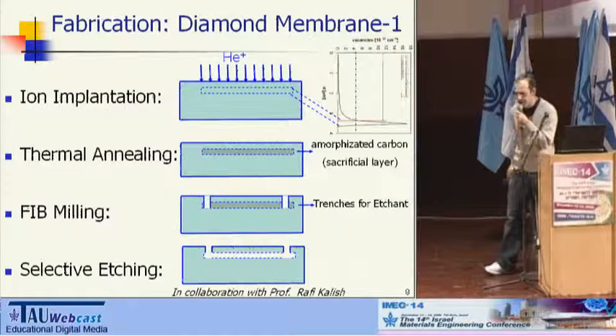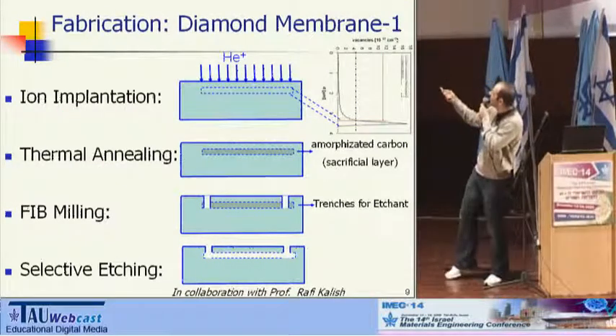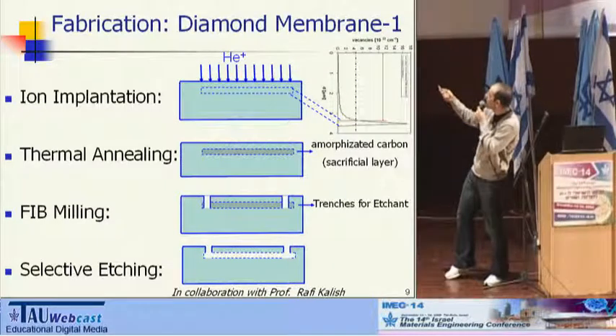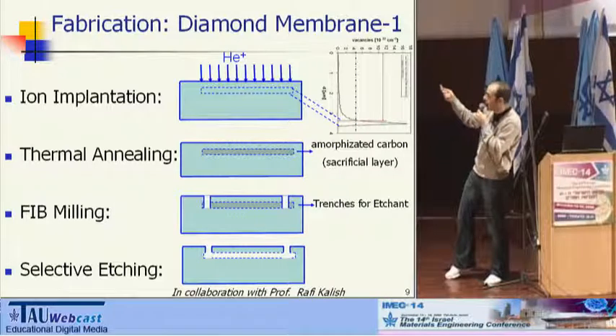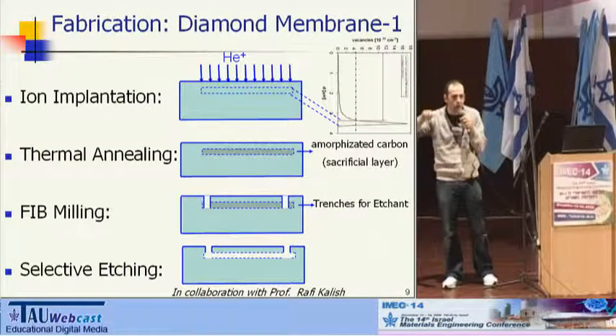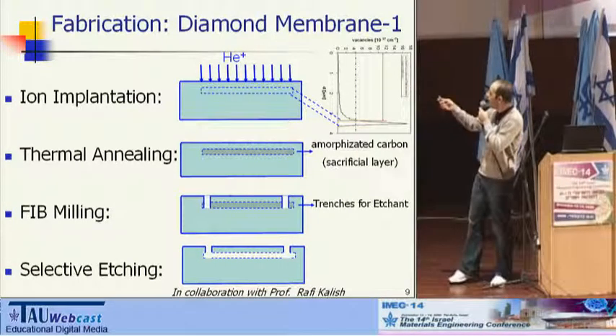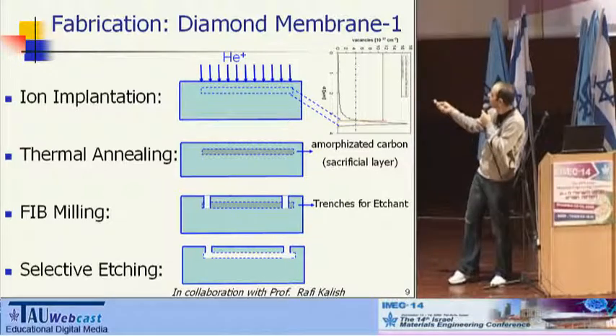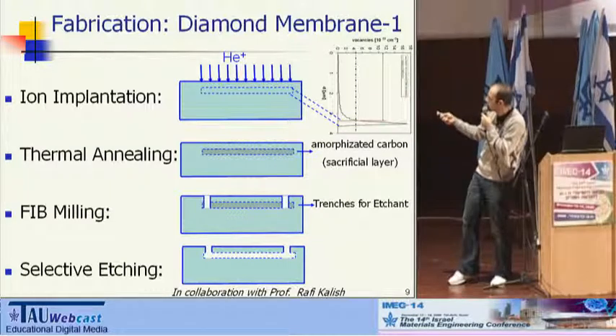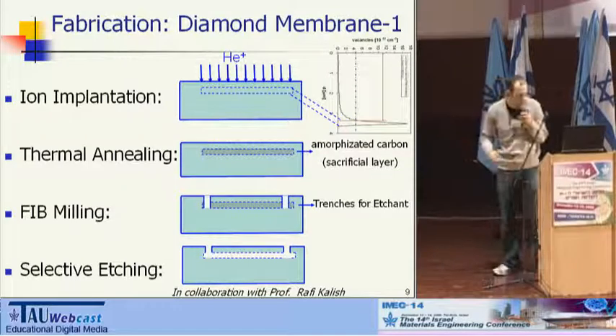So let's start with the membrane. We've got this type 1b diamond sample. We irradiate it with helium implantation. This helium implantation forms a buried damage profile, and this profile under subsequent thermal annealing is graphitized when the damage density is higher than a certain threshold. It can be etched out, and we obtain a freestanding membrane.